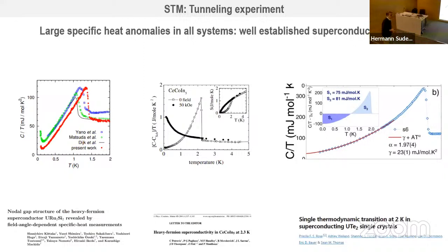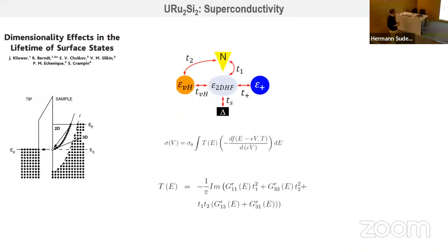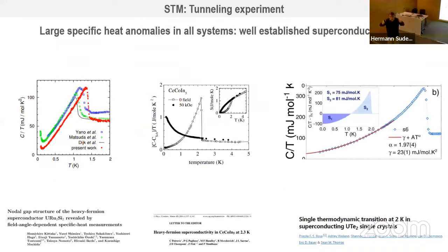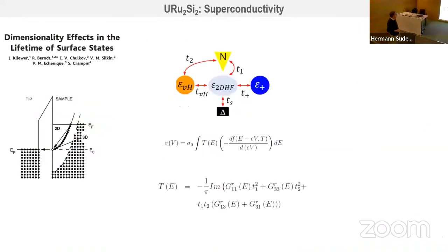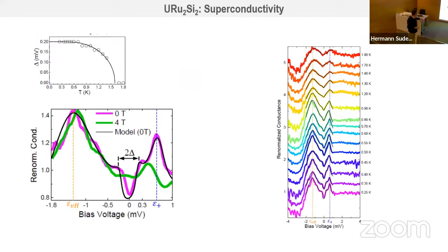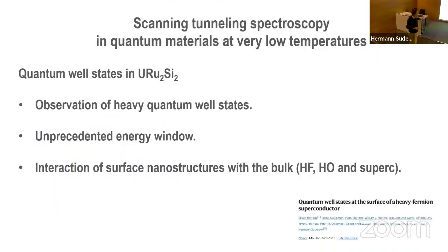And this is absolutely incompatible with the curves which I showed you previously. It would rather be compatible with the curves which I have shown you in the beginning, where you have a high density of states and zero states inside the gap. So the way to understand this, we believe, is that we have to understand these curves at the surface through a connection to these two-dimensional electrons. So we have to take into account that there are anomalies close to the energies of the superconducting state, which actually have a very strong influence in the tunneling conductance curves. And when taking this into account, we have a good model where we can fit our data and we can understand the changes as a function of the temperature and follow the superconducting gap. So there is a very strong influence of these two-dimensional states in what happens in the STM at low temperatures.